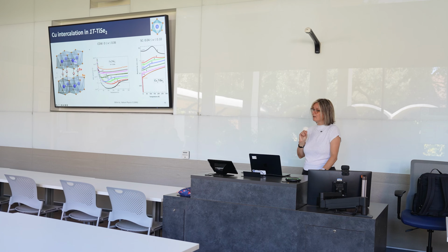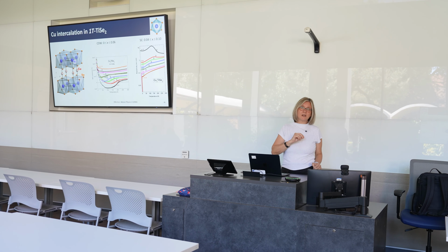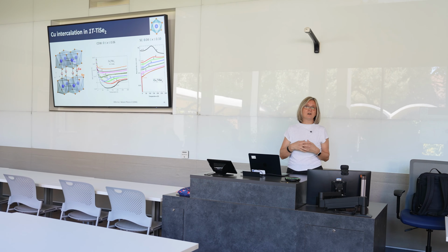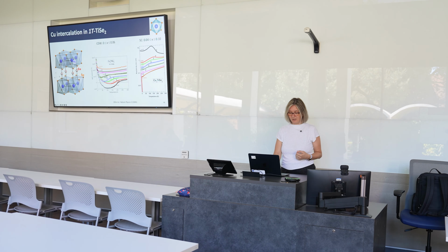Titanium diselenide is one of the very few TMDs which does not show superconductivity without pressure and without chemical doping or intercalation. So it was surprising, and it was one of the first examples of inducing superconductivity chemically once we intercalated copper. When copper is intercalated, here I'm showing the susceptibility starting with that of the pure TiSe2 in black, and the other curves correspond to increasing amounts of copper.